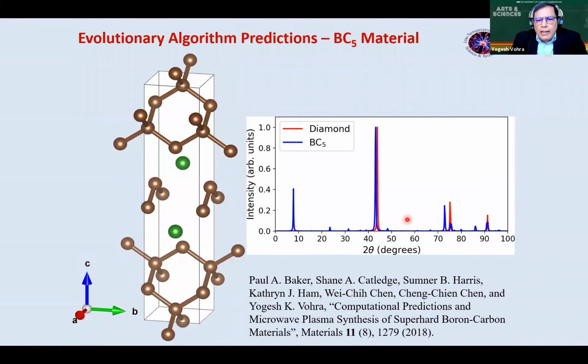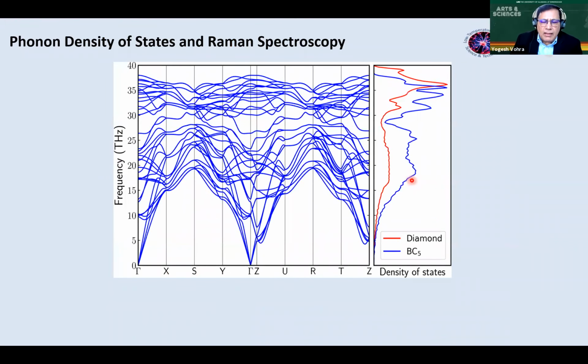So Dr. Cheng-Chien Chen has also predicted a BC5 material, which means that for each boron atom, you have 5 carbon atoms. It has a very stable structure, which has been predicted. By upping the boron concentration in the plasma, our goal was to really make this BC5 material. And the BC5 material predicted by theory is actually very stable.